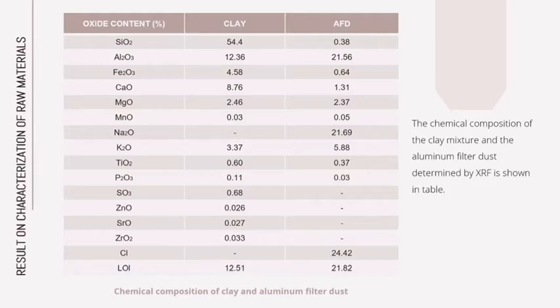The relevant proportion of calcium oxide, 8.76%, could be derived from the high presence of carbonate, as indicated from the loss on ignition observed. The chemical composition of AFD shows a considerable amount of aluminum oxide, 21.56%, and alkaline oxides, sodium oxide with potassium oxide in 5.88%, and smaller quantities of ferric oxide, 0.64%, also calcium oxide, 1.31%, and magnesium oxide, 2.37%. The large amount of flux oxides in the waste could decrease the firing temperature or the time of the ceramic brick, saving energy in the process.